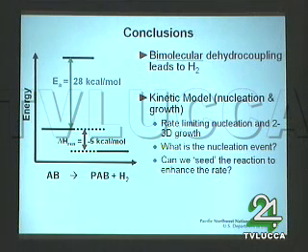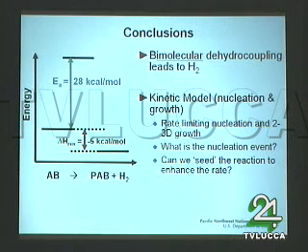So, a bimolecular reaction, not a unimolecular reaction. Kinetic growth, nucleation, and it's somewhere between this 2 and 3D growth. And so the critical question really is, what is this nucleation event? Because if you have that, you can possibly enhance the kinetics. And so we can seed the reaction and get the hydrogen off at lower temperatures or faster rates at the same temperature. And so that sort of wraps it up.